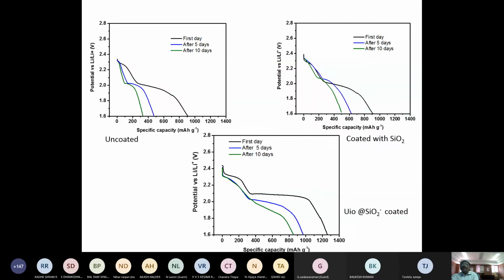And finally, what we have done is we have stored the lithium sulfur cells for a longer time. The left hand side figure A shows the uncoated membrane. So on the first day when we charge and discharge, the cell was able to deliver only 900 milliampere hour per gram, and after 5 days it was able to deliver only 500, and after 10 days when we charge and discharge the system, that uncoated membrane was able to deliver only 300.